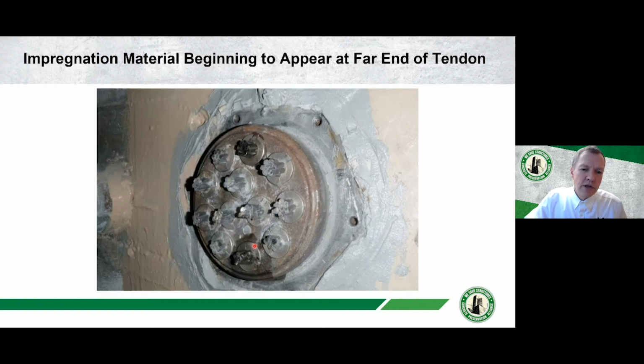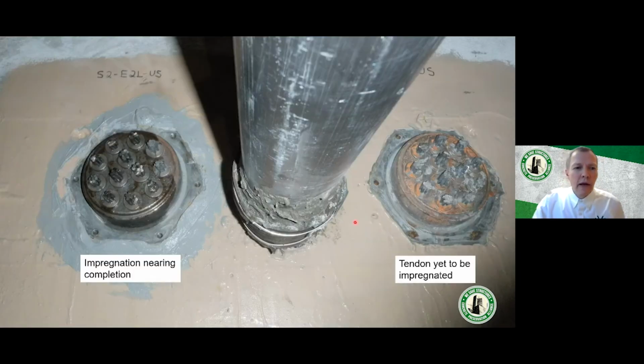And here you can see the material starting to seep out of one strand down here and another strand up here. Continue to wait. And the tendon on the left, I don't think material is coming out of these 2 strands at the time when the photo was taken, but you continue to wait until the material is visibly coming out of all of the strands at the other end. And it's very obvious visually when that's happening and when it's not.